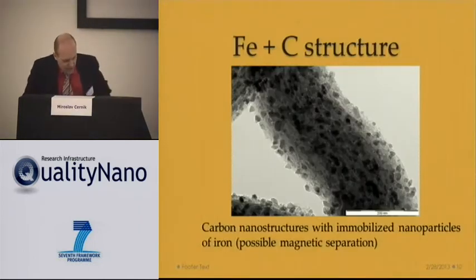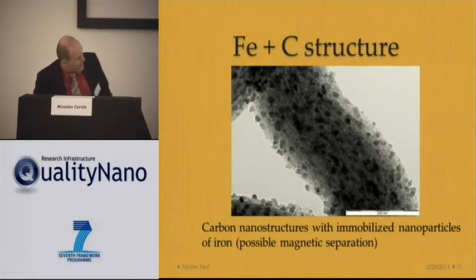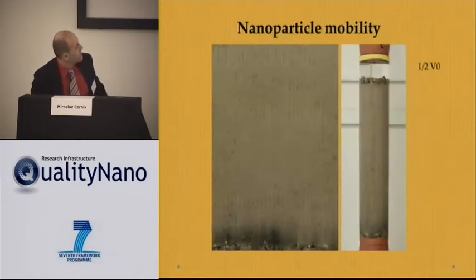Here is only a picture showing the iron together with carbon, where we have the small iron particles on the carbon structure, and the advantage of the material is that it can be separated from solution by magnetic separation, because the iron goes to magnetite.